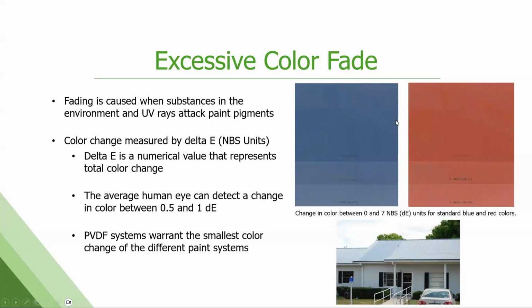And these are actual color cards I have here, the blue and the red here, that shows starting color at the top, a delta E of 5 units in the middle, and then a delta E of 7 units at the end. So you can kind of visually see, right? If the warranty says will not fade more than a delta E of 5 units in 20 years, they're saying that you might have some color fade between these top two, but no more than that in that time period. And what we find, most people, if your roof is fading evenly, after 20 or 30 years, no one really notices, right? When we get color fade complaints, it's usually because part of the roof looks better than the other.